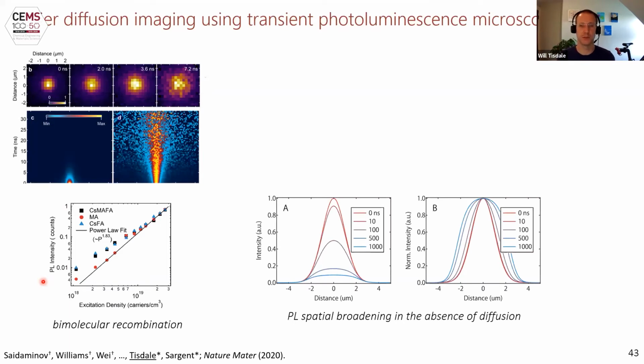Well, this is a problem if you're trying to measure the spatial broadening of your photoluminescence, because your charge carrier density is higher in the center of your excitation area than at the edges. So the center is going to recombine faster than the edges, which leads to a broadening of the full width half maximum of your spatial photoluminescence that you measure, even in the complete absence of diffusion, just because of the nonlinear relationship between the photoluminescence and the charge carrier density.